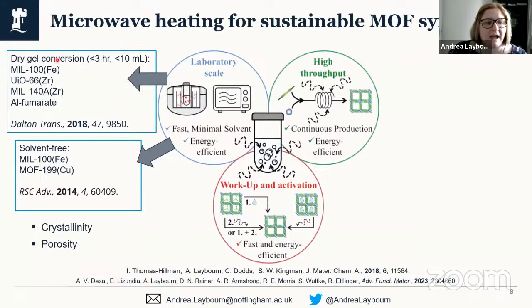The two that I wanted to focus on today were the dry gel conversion, which was developed by Tanner et al. And this is using a reactor where you have a solvent at the bottom and then you have a shelf essentially with solid reagents which have been finely ground together, and you're using microwave heating to evaporate the solvent into the layer above where the solid reactants are, and then the reaction takes place in the vapor phase. This is a relatively fast process, under 3 hours compared to the conventional heating processes. And you can use solvents of less than 10 milliliters. So this is reducing the impact of the solvent there.